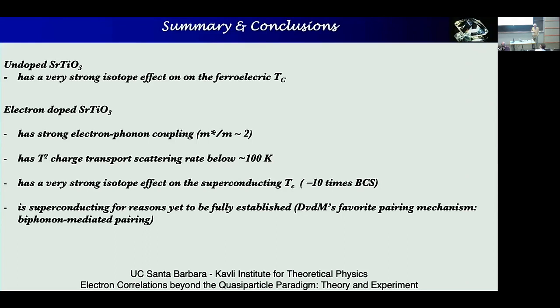Kamran? Well, Dirk, I agree with all you said. I just want to make a comment about mass at high temperature. This is actually related also to Shankar's question. It never becomes T-linear resistivity. So there is no T-linear resistivity here. The way we understand it, if you put the numbers, the mean free path is ridiculously short. And one way to remedy this is to suppose that the mass is increasing with temperature, not decreasing, but increasing. This is what comes also from thermopower.